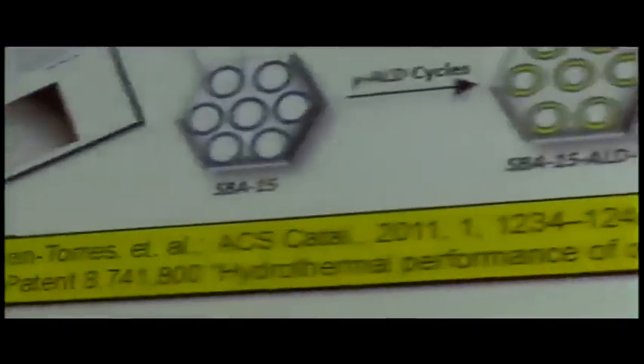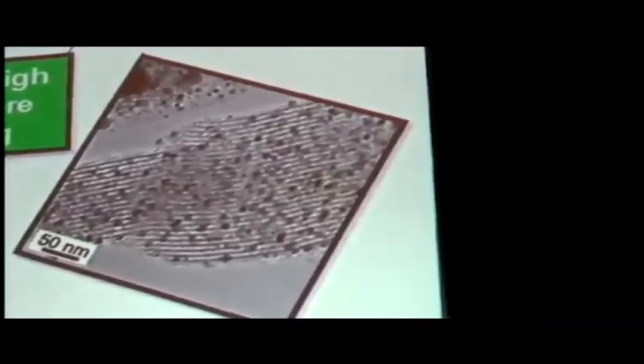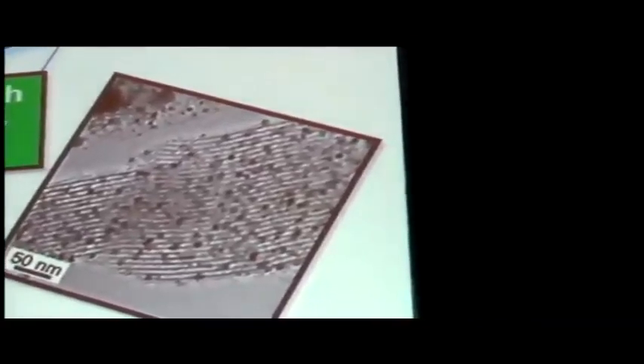we can coat both the inside and the outside of the particle, and then we put the same material in boiling water and retained almost, I think it was something like 85-90% of the total surface area there. And what you can see in the lower right-hand corner is a TEM of using this material for supporting platinum particles. This is a picture of that after reaction conditions, and the pores remain the same there. And we've got a patent that just was issued for this type of material.